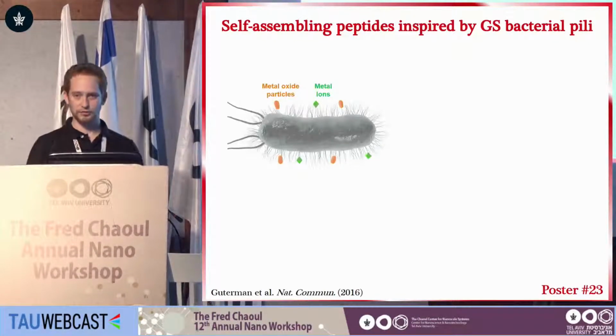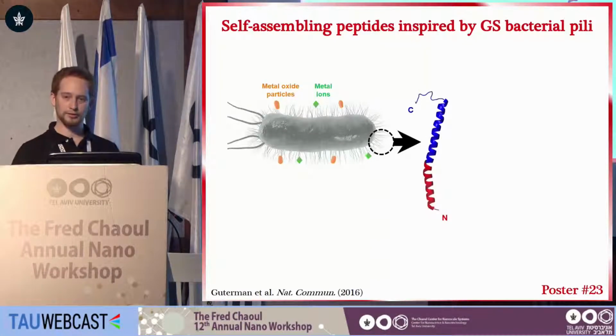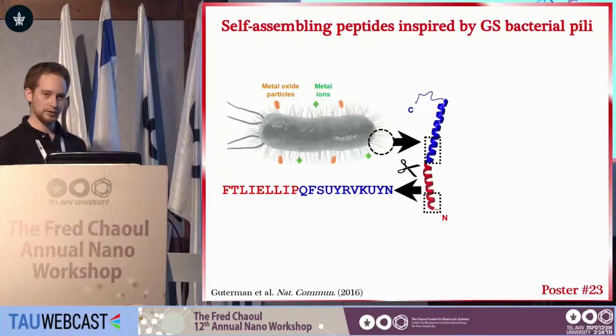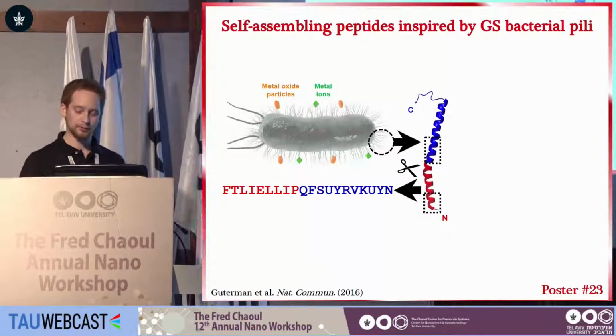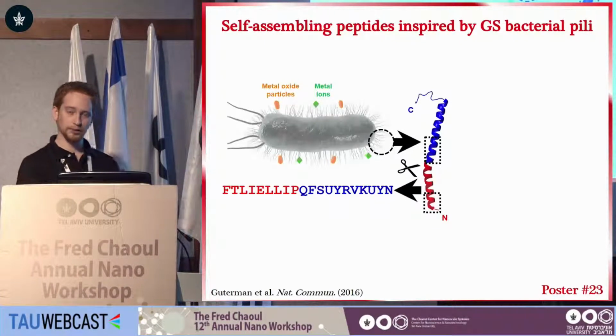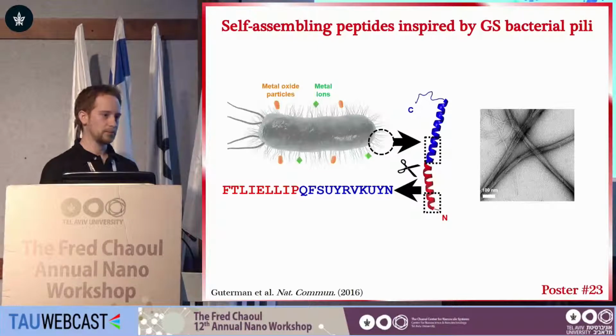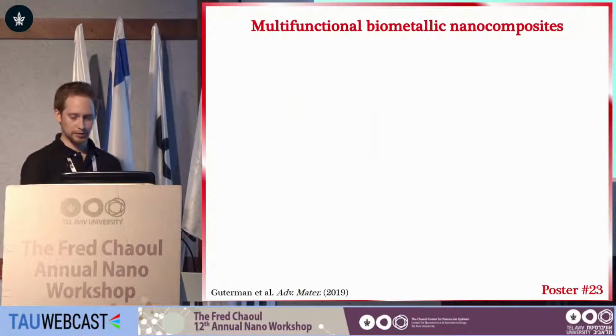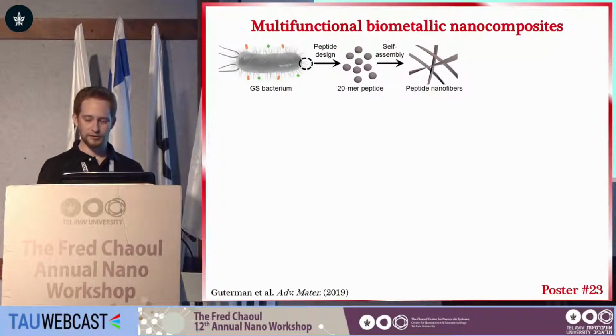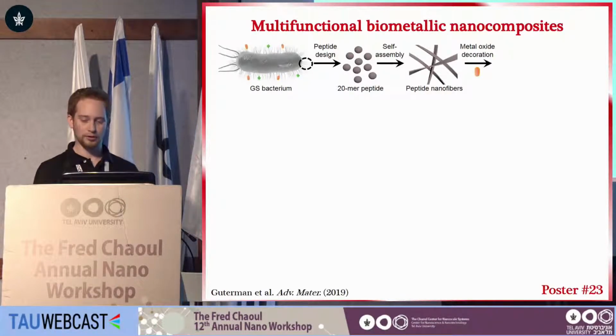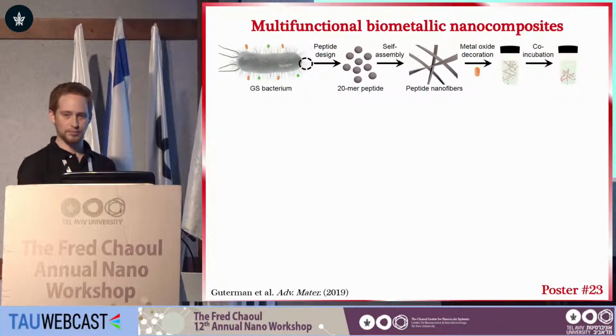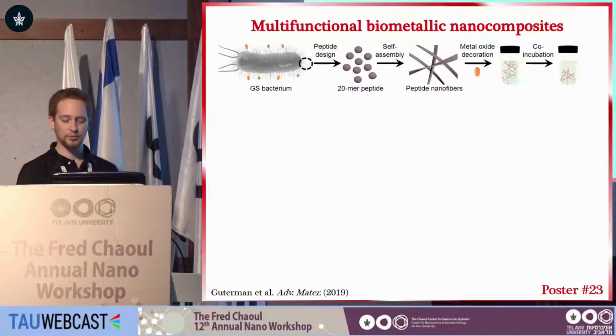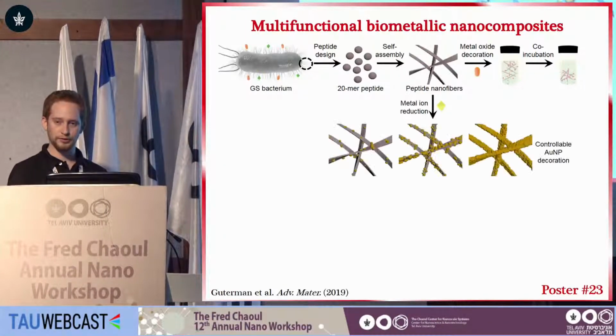So there's an interesting biological story behind this, but what we're doing is we're looking at the amino acid sequence of the monomer of these fibers, and we derive short peptides from it. So there's, for example, here a 20 amino acid long peptide derived from two distinctly different regions of this protein that self-assembles into nanofibers that are similar to the native fibers in certain aspects. And one thing we did with these fibers, inspired by the native system, is interacting them with metal oxide particles, where they co-incubate and become decorated by these particles, or interacting them with gold ions, which become reduced into nanoparticles, and they decorate the fibers to very high extents.